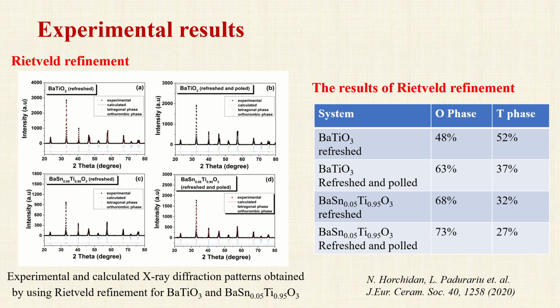The Rietveld calculation results are in agreement, at least at a qualitative level, with the predictions of the models. Both types of systems are characterized by phase superpositions in the unpoled state, and the amount of the orthorhombic phase increases after poling towards 25 kilovolts per centimeter, with a higher amount of the orthorhombic phase in the solid solutions.